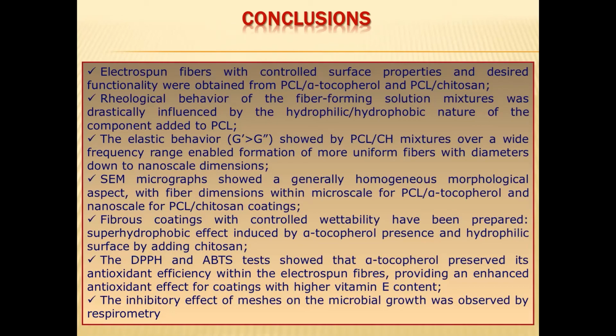Fibrous coatings with a controlled wettability can be obtained, with a superhydrophobic effect induced by alpha-tocopherol presence and a hydrophilic surface by adding chitosan. The DPPH and ABTS tests showed that alpha-tocopherol preserved its antioxidant efficiency within the electrospun fibers, providing enhanced antioxidant effect for the coatings with a higher vitamin E content. The inhibitory effect of meshes on the microbial growth was observed by respirometry.